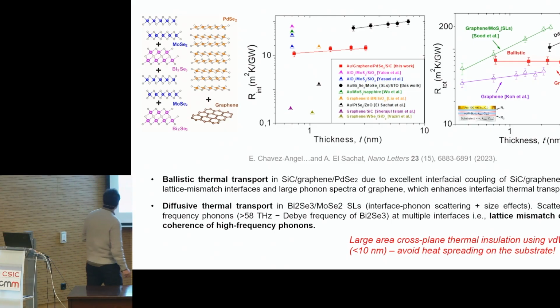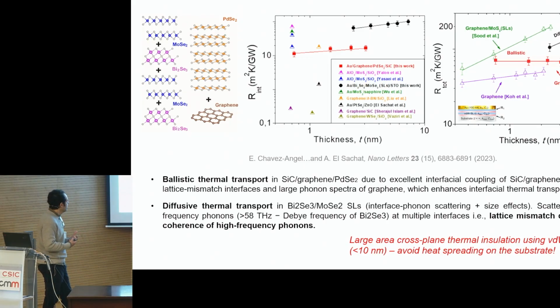And if we measure this, if you look at this graph here, you see the thermal resistance of the film that we measure. What we found is that we have ballistic thermal transport in graphene palladium diselenide heterostructures, since we don't have any lattice mismatch interfaces, and we have a large phonon spectra of the graphene that gives us phonon propagation in the cross-plane direction as well. However, in the superlattices, we have diffusive thermal transport due to the fact that we create this kind of interface phonon scattering between the interfaces, and this is the result.